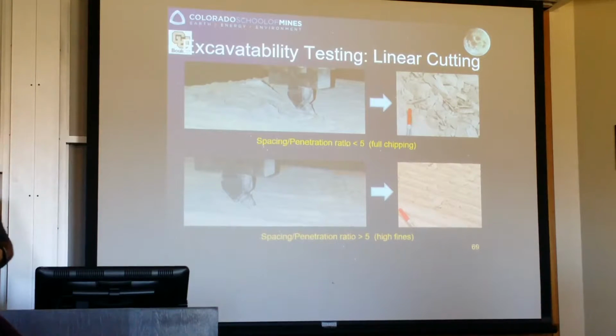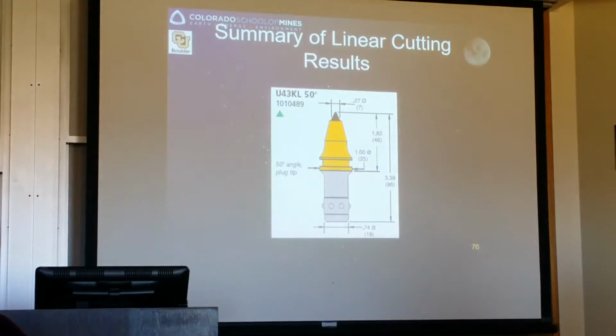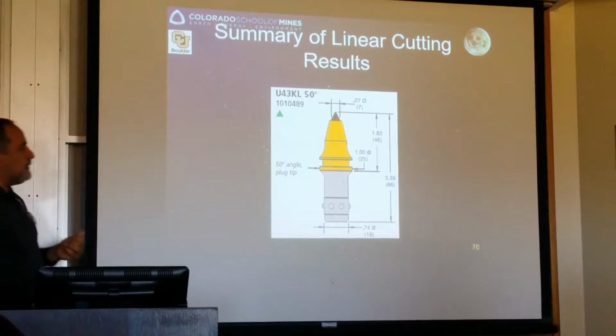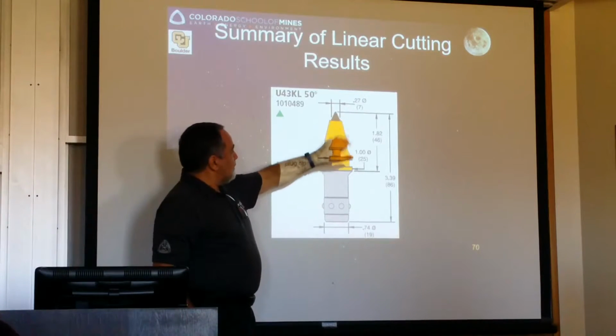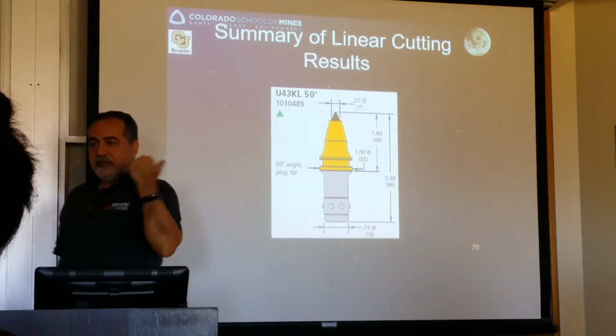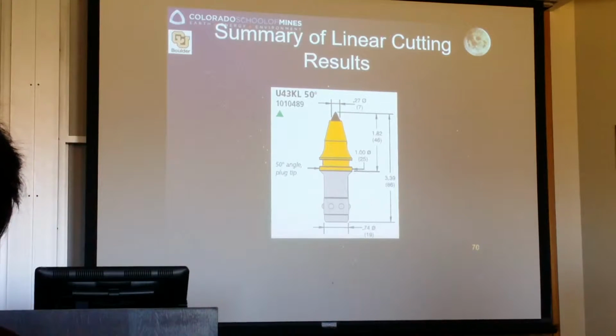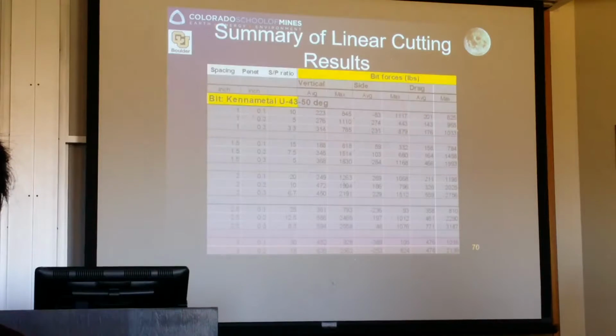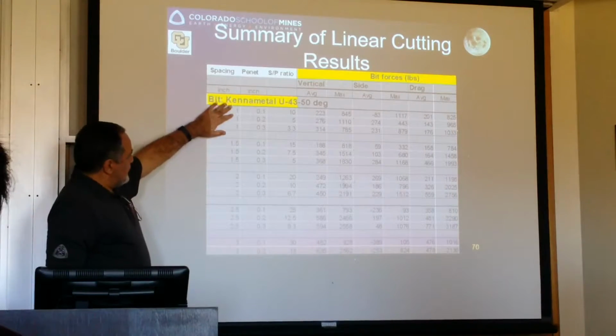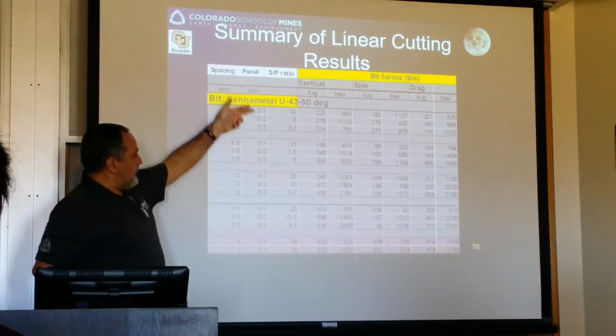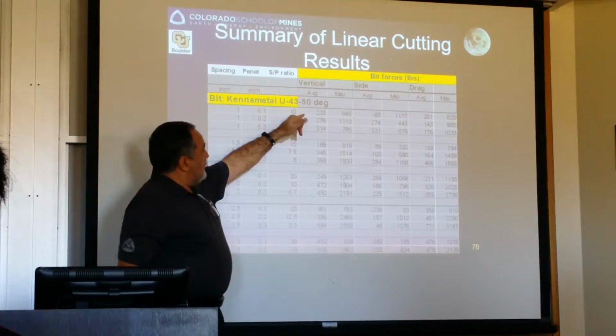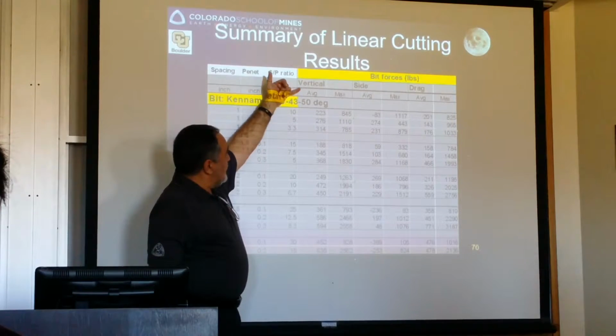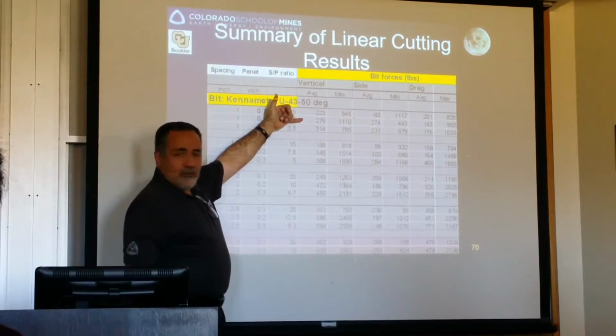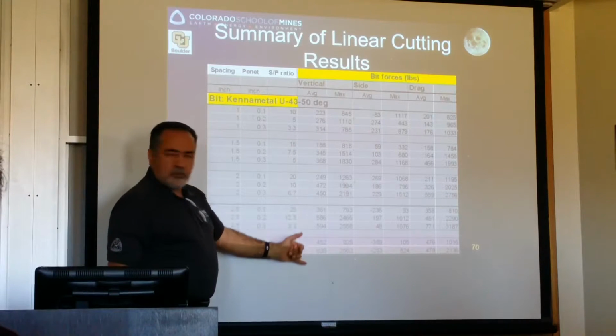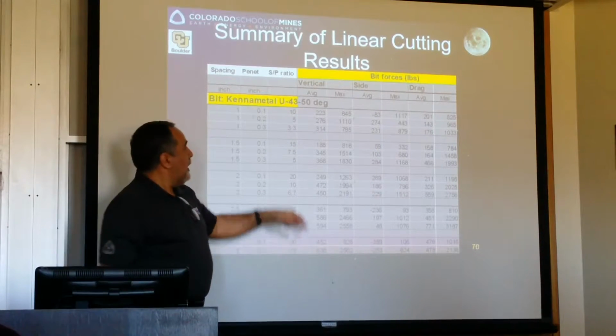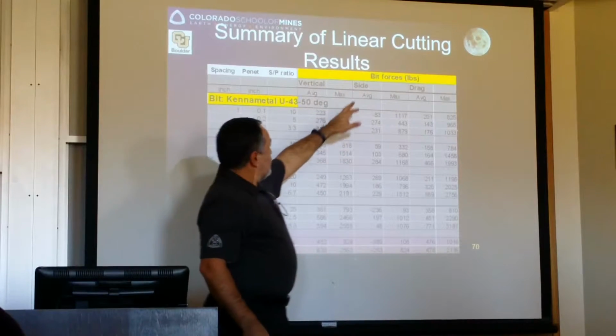So we did a lot of tests and came up with the result. This is the bit we used, not a dull bit, a very sharp bit with a very sharp nose. And of course, the trade-off is that the life of the bit may be lower. That's the bit we used, and these are the results. So for different spacing between the cuts, different depth of penetration, and that bit, we measured the bit forces. So 200 pound, 300 pound, 500 pound, and so on. Okay, that's not bad. It's doable. This is the vertical load. This is the side load.